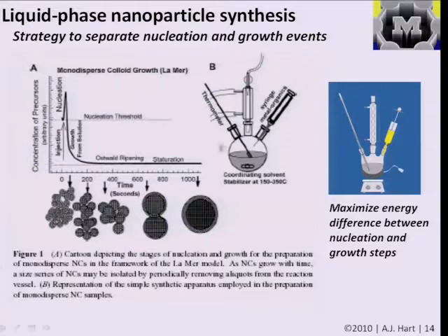So a typical apparatus for making nanocrystals in solution might be, for example, a glass vial here, or a glass flask here, which is under controlled atmosphere. So, for example, it contains no air. You can bring a purge gas in here, and it's, for example, sitting on a hot plate, so you can control temperature, and maybe that hot plate has a stirrer, so you have uniform circulation in the liquid. And you have, say, a thermometer, so you can control the temperature or know the temperature. That might be fed back to the hot plate. And you have a way of injecting a precursor solution.